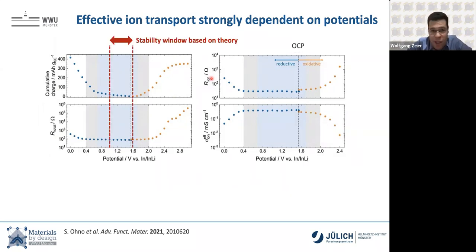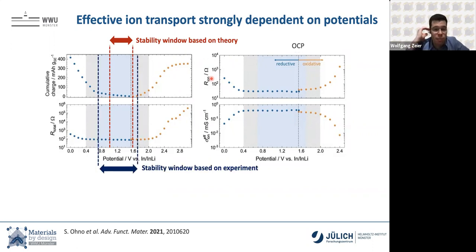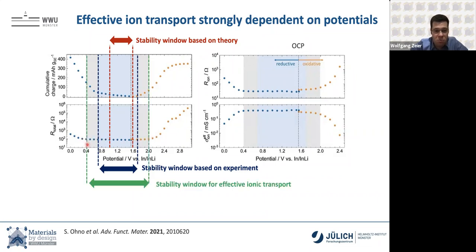And here the red dashed lines would be the stability window based on thermodynamics, so based on Yifei Mo's calculations. In blue, this is the stability window that we get from our CVs. And you see up here in the charges that as soon as we hit that, some charge is flowing. So we're really decomposing our solid electrolyte. Usually not a good thing to decompose your electrolyte in a battery, but the resistance doesn't change up to a certain higher potential and lower potential. Here shown in green, the total resistance doesn't change, the ionic resistance doesn't change, and your effective ionic conductivity also doesn't change. That means we have some sort of stability window for an effective ion transport. We can run our electrolytes outside of their stability window, and it's not bad for the battery.